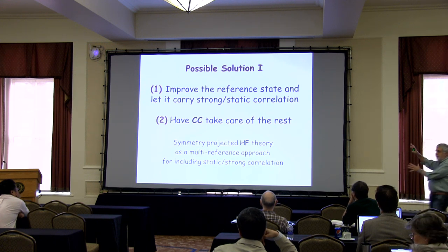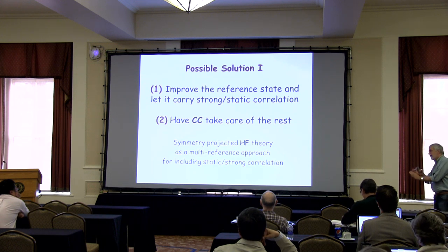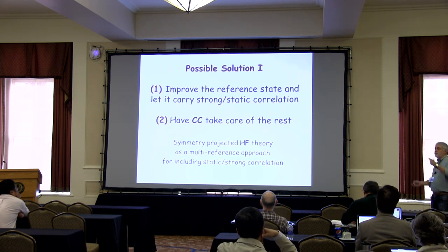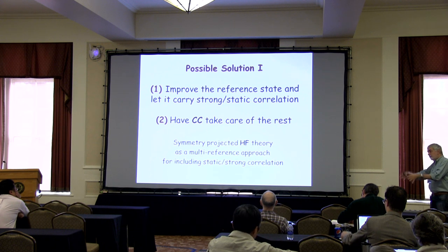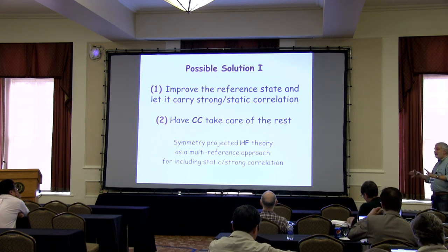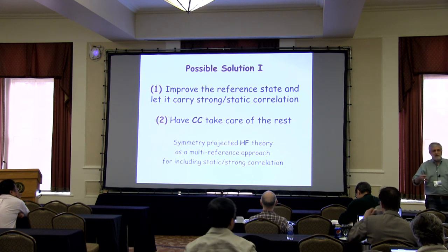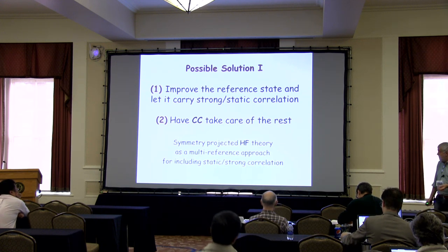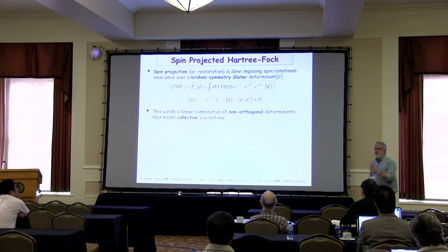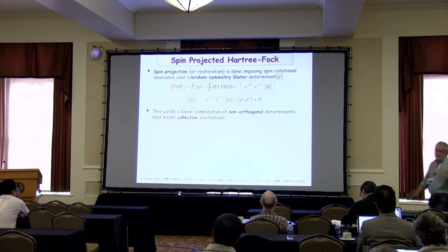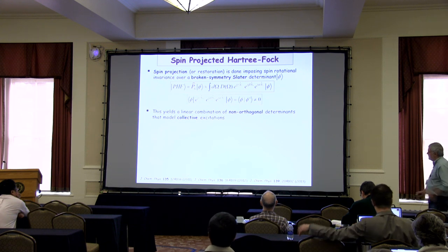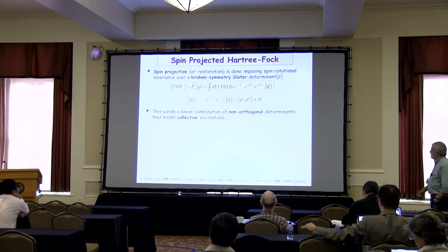And this was highlighted, Martin mentioned this, the fact that if you do an RHF calculation on C60 and you optimize the cage, you get an icosahedral ball. Perfect. But somebody in Martin's group does the Hessian and finds out that that thing is unstable. If you allow the spins to be up and down and break spatial symmetry and break spin symmetry, they do that, and the energy goes way down. The problem is now we reoptimize the cage, and it's non-icosahedral. So something is very wrong, because there's one thing we know about C60, is that the NMR has a single peak, which means that all the carbon atoms are equivalent, so it is icosahedral.